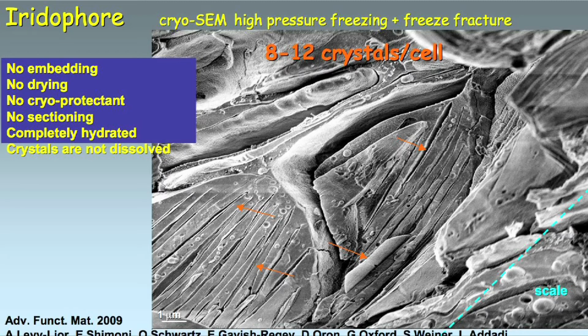So this is really the manner in which the cells are juxtaposed under the scale. And then we can see very well in these very thin slits, and we can see the crystals. Each crystal is enveloped in a membrane that's called a crystal chamber. And you can see one here that during freeze fracture was left over on this side, and you can in fact appreciate how thin they are. And there are, as I said before, about 8 to 12 crystals per cell.